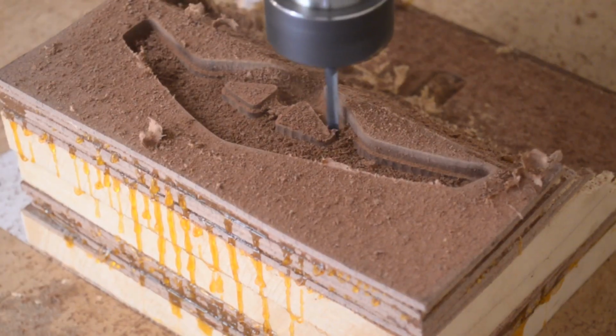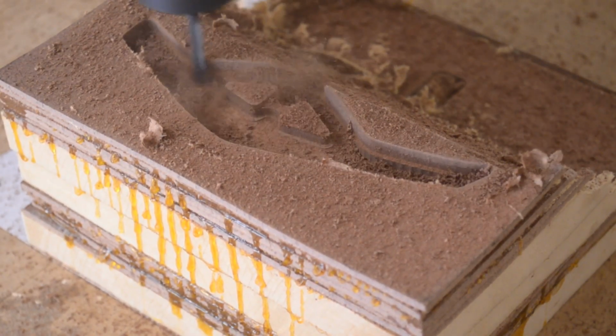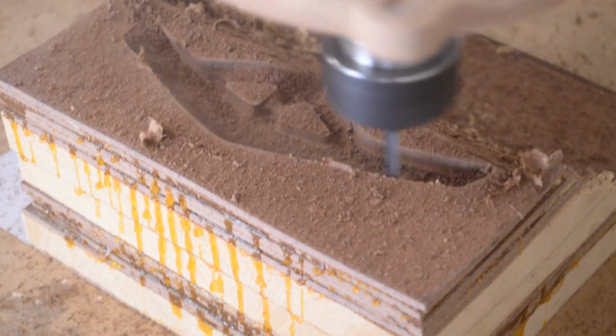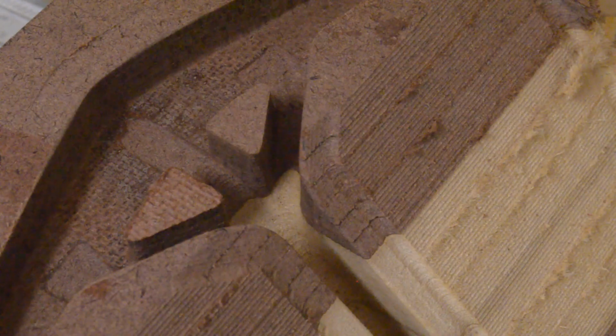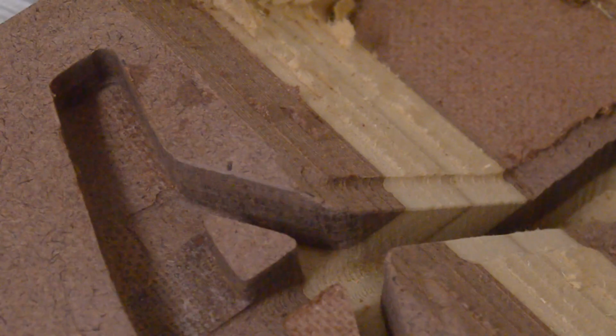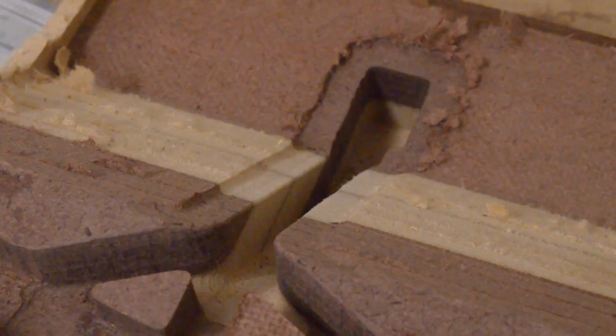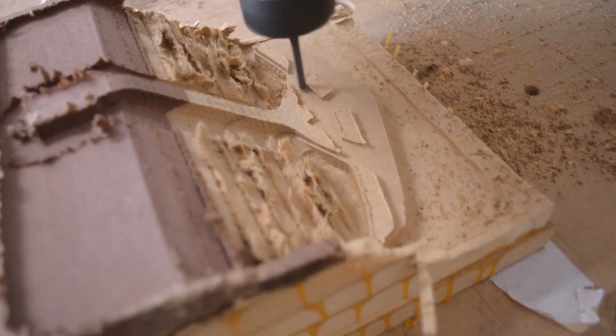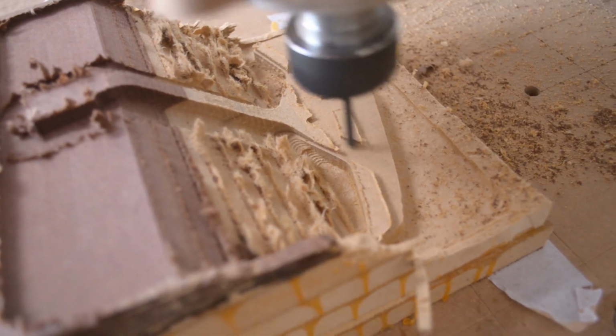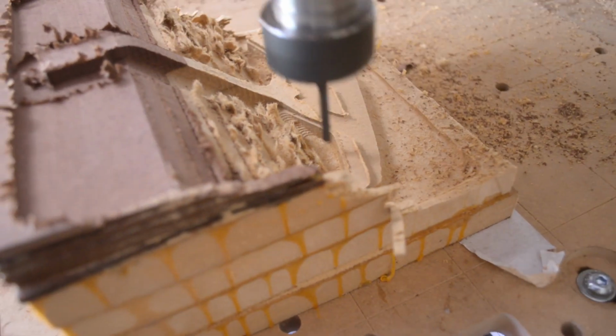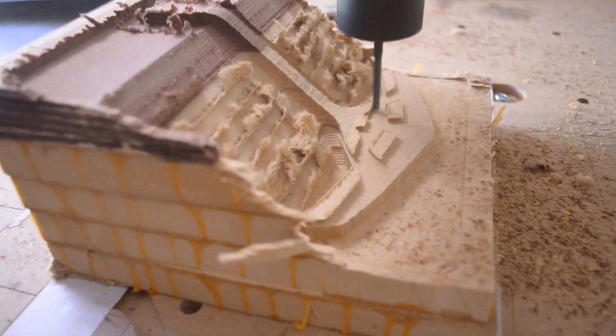So the first thing we need to do is CNC machine both the female molds and the male molds. And really the most important thing with this is making sure that we have a good surface finish on both the surfaces that are going to be in contact with the carbon. And if we don't, it's going to show up in our part once it's cured. And you might ask, why don't I just 3D print these molds? I really got a bad surface finish out of doing this. So I tried it and it didn't work for me. So we're onto the CNC machine.